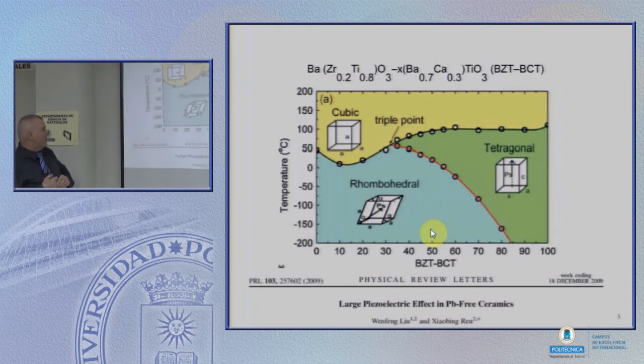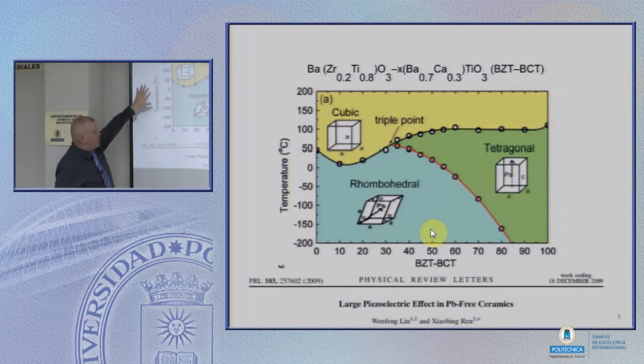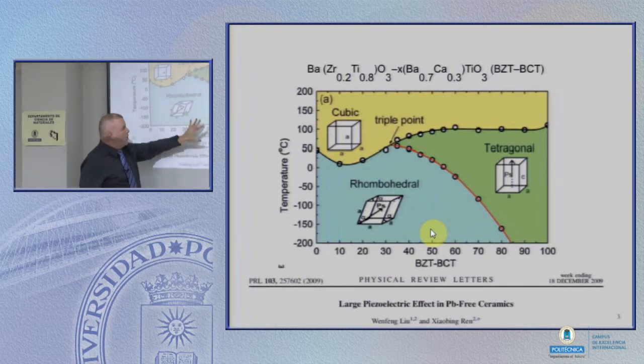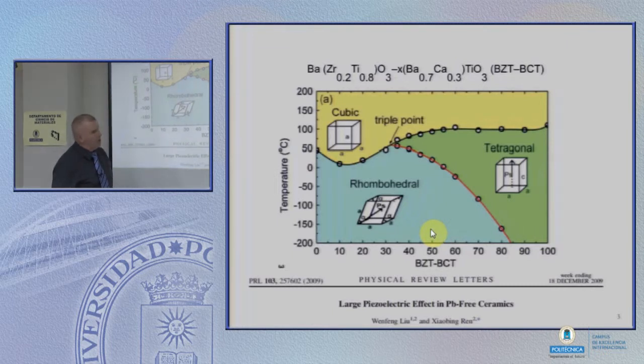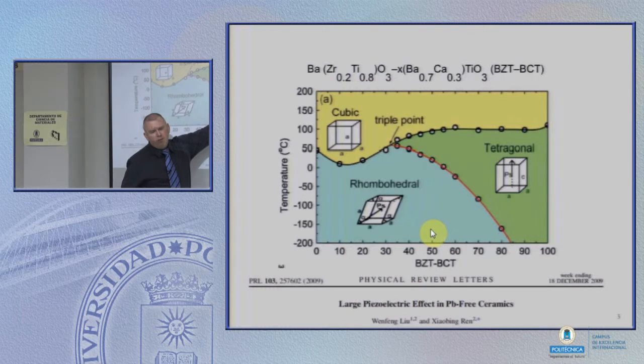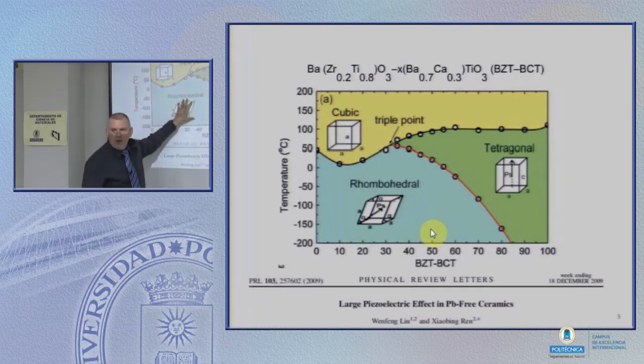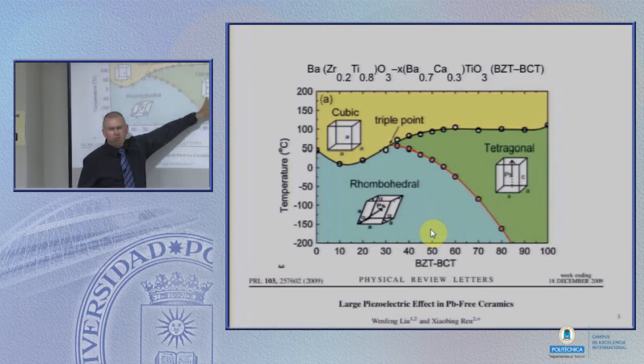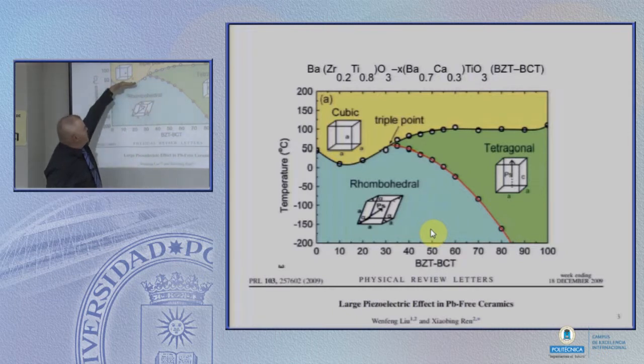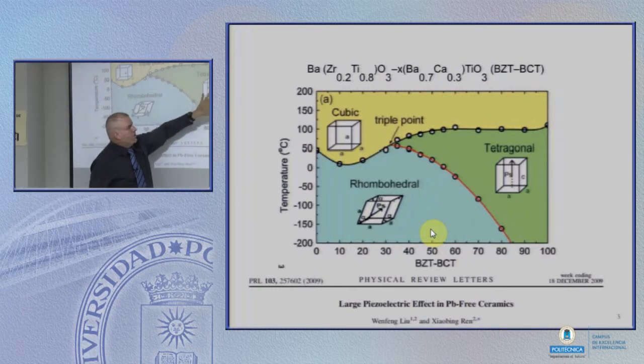It was this system, which is shown here. So it's essentially a pseudo-phase diagram. This is temperature. This is composition. It showed what is classic to piezoelectric materials, which is that we tend to have two lower symmetry phases adjacent to one another. In this case, it's rhombohedral and tetragonal. And at a higher temperature, it's a non-piezoelectric material. It's actually cubic. So this is a piezoelectric ferroelectric material.